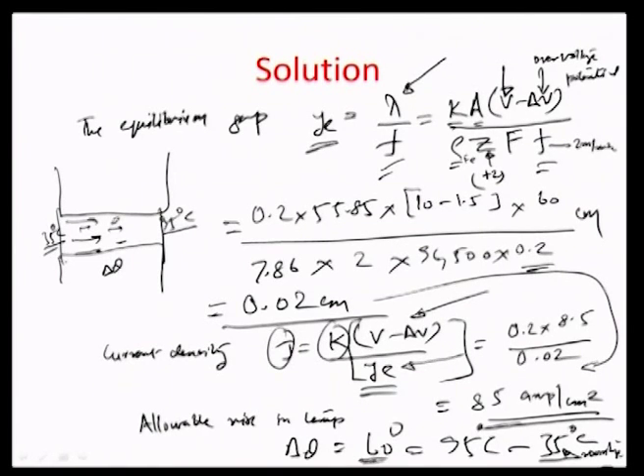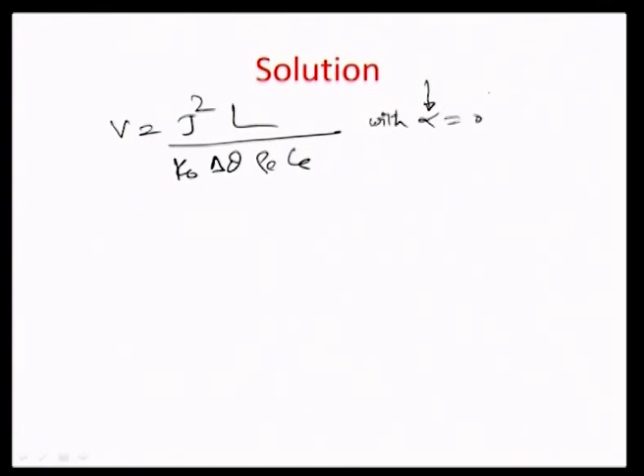So, therefore, now we can calculate the design velocity, which is given by J squared times L by K0 delta theta rho e C e. Okay. And the temperature coefficient of change in conductivity we assume here as 0, just to make things simpler. Okay. So, there is no change of K with temperature, and we are actually taking the K at more or less the same ambient condition of 35 degrees Celsius here. So, by plugging in all these values into J squared L by K0 delta theta rho e C e, the total length to be spanned is 25.4 millimeters.